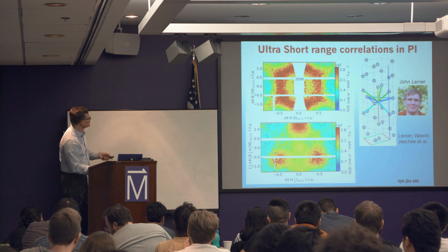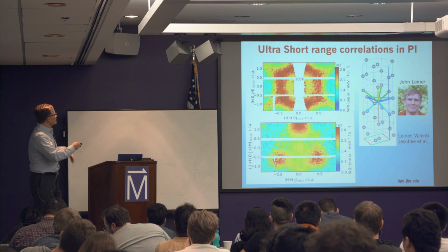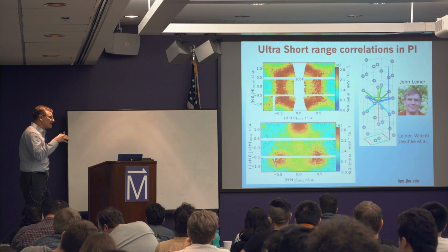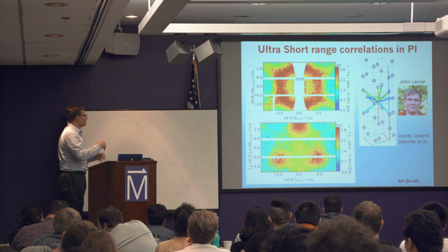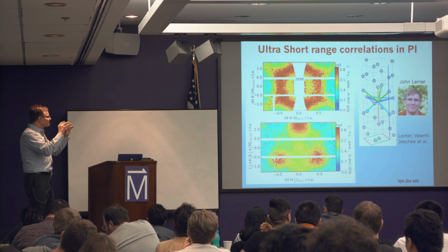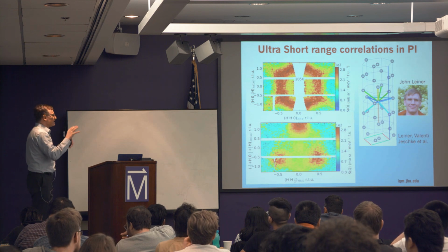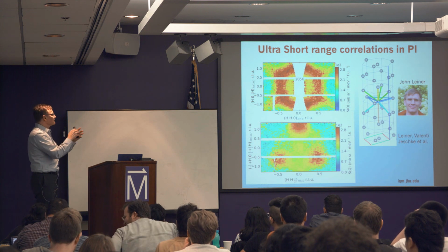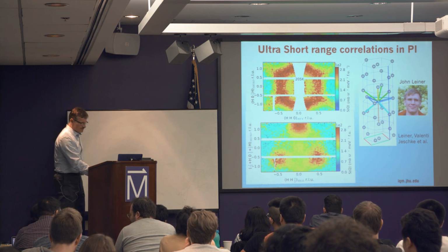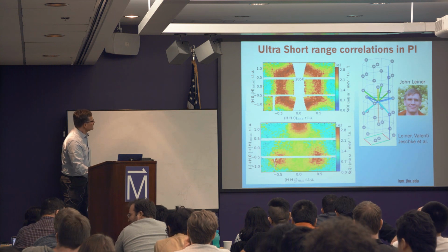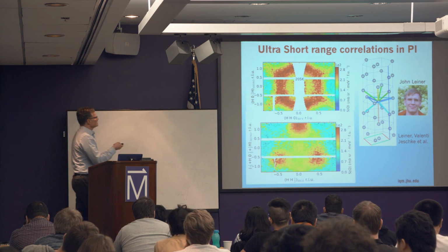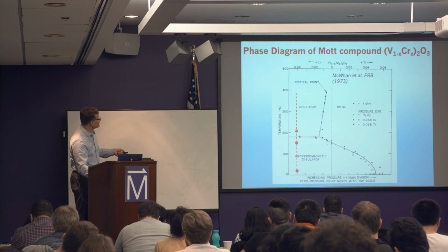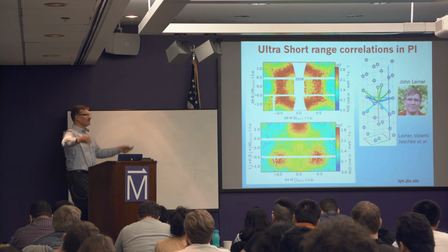We've got these very broad structures, but there are some pretty well-defined edges and features present. That caught our eye because we've seen that in other frustrated magnetic systems, that they have these broad structures but with certain specific features. Those tend to be associated with what I call satisfied local constraints, which produce these kinds of very broad patterns in momentum space. Now, the question was, why does this system have such a broad pattern, even very close to the phase transition? I'm sitting here almost going into the ordered state, but I have scattering everywhere in momentum space.